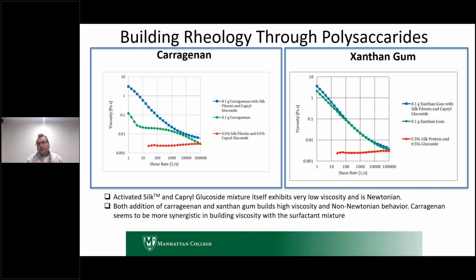So here we engineered the interactions between the carrageenans and the protein and the biosurfactants. So it's a ternary system, and we optimize that interaction. And again, here you need that sort of high throughput formulation development in order to get to this level of optimization. And this is just for a 3-component mixture, right? But there are many formulation variables which you can play around with, right?